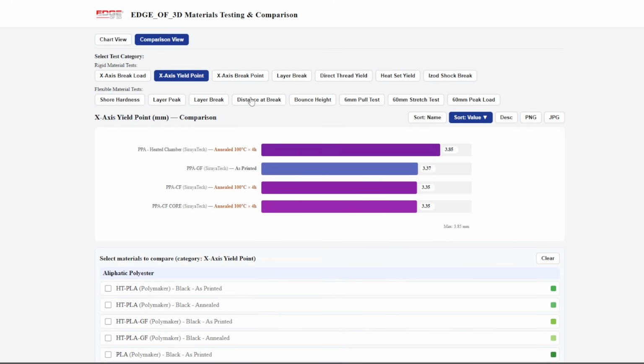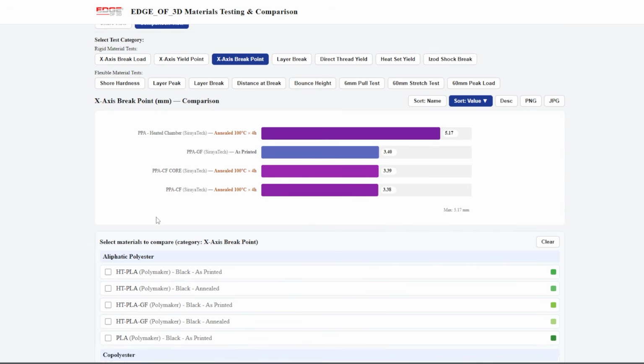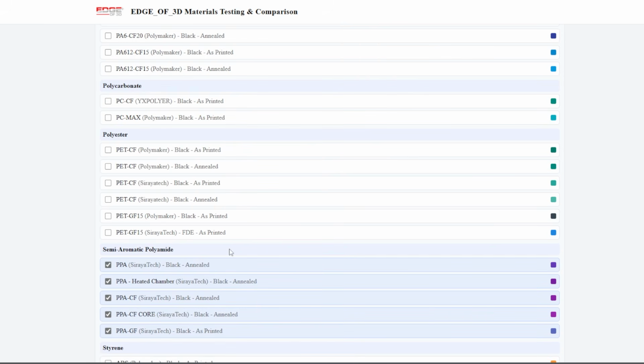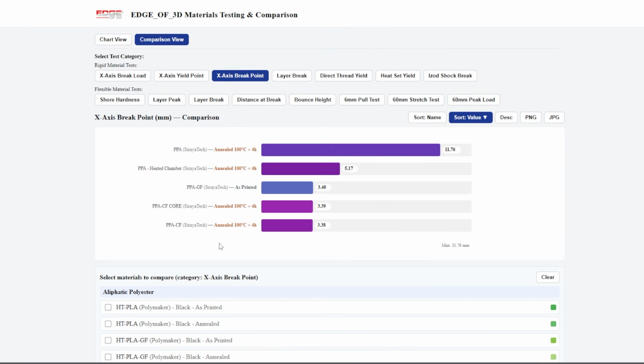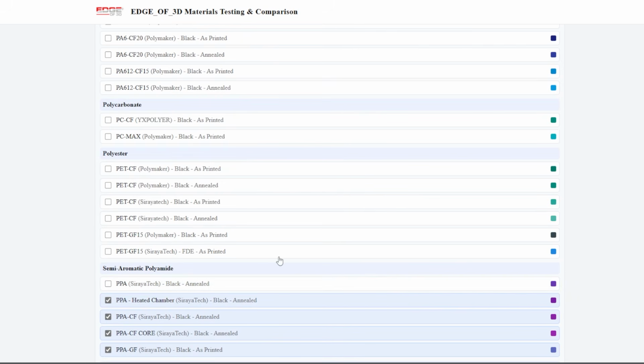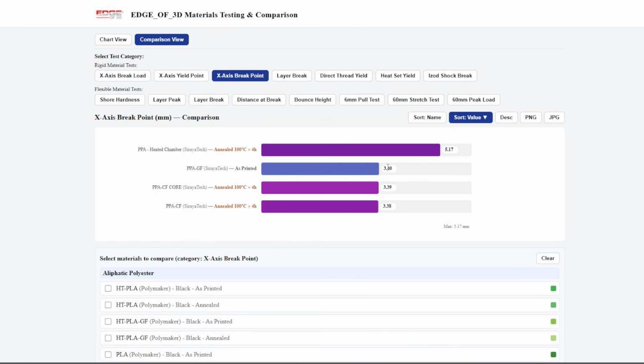So 3.35, 3.37. The break point is where it breaks after it peaks out. And as you can see, 3.38, 3.39, 3.40. Basically, it broke where it finished stretching, or where it peaked out at. What you see here with the PPA, though, is it peaked out at 3.85 millimeters of pull, and it did not break until 5.17 millimeters, and that's on the annealed. If I go to the unannealed, or the stuff that wasn't printed in a heated chamber but was also annealed, it stretched a lot further. So anyway, we're talking about PPA glass fiber today.